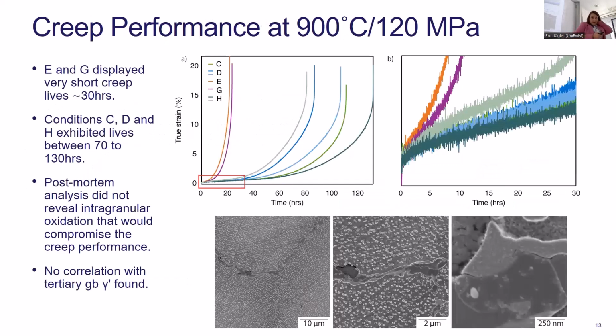Now, the more interesting results came from the creep. So the tensile, we didn't really see any changes in the microstructure. We weren't expecting massive differences in the tensile. That was sort of logical. The creep, we were expecting to see a lot more differences, but they didn't really correlate very well. So we didn't manage to get good data from some of the conditions.